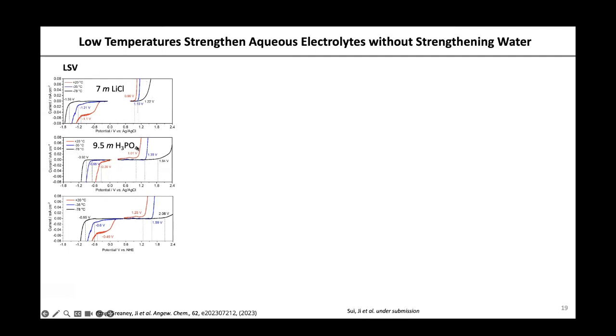Now we combine the two electrolytes to form this more accurate map of water, because you cannot use the OER side for lithium chloride because chloride will be oxidized. So this is not oxygen evolution, this is chlorine evolution. So we cannot use this part for this electrolyte. Now for phosphoric acid, we cannot use the HER side because it's not about water, it's about protons, right? But if you combine these two electrolytes, then you can provide a whole picture of how water behaves at a low temperature compared to the room temperature and a relatively low temperature. So by lowering the temperature, water becomes a less reactive solvent. It's inert, right?